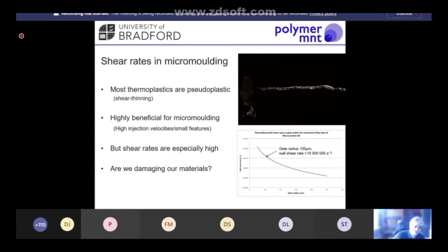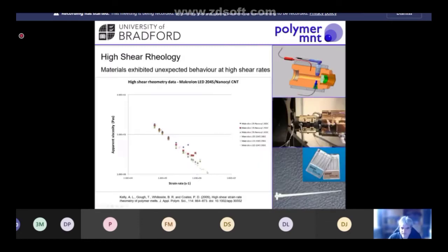One thing we do have to be conscious of is the shear rates that we're exposing these materials to as well. In an injection molding process, we're injecting at quite high velocities. And what this can do is cause a breakdown of materials in the process. And so we do quite a lot of work on understanding the shear rates within the process. We can look at the viscosity of the materials at these shear rates, and we can use this information to make sure that we're not going to cause a breakdown of the polymer or the drug within the polymer caused by excessive heating during the molding process. So we've done a lot of work in this area for optimizing materials based on this kind of information for our application areas, including the dental component that I mentioned before in the early slides.